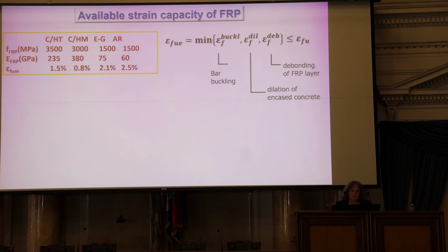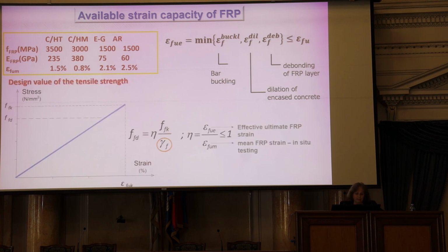You can use a smaller amount, which is determined as the lowest value that would lead to failure from among a number of possibilities. For instance, buckling of interior reinforcement can cause a rupture of your FRP. So you have a limiting strain capacity of the FRP, which is related to the setup that you're using, and that buckling strain capacity limits how much of your FRP you can use. Dilation of the encased concrete can rupture the FRP, particularly at the corners, which you saw we chamfered and rounded to minimize the stress concentrations, or we can have debonding of the FRP layers. All these values are strains that are limited by the mechanics of the failure mode, and they are generally less than what the FRP can offer.